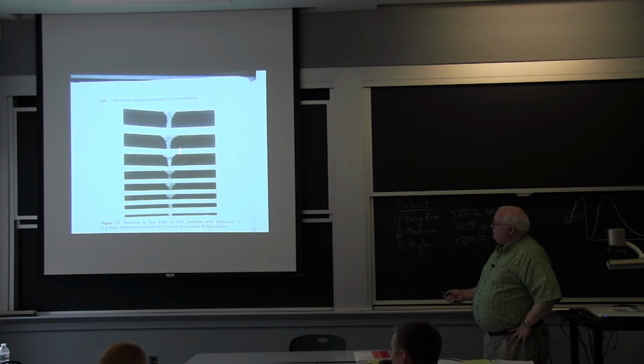So I talked about distortion, and there were a couple of things I wanted to show you. This is actually 5083 aluminum, electron beam welded from a 1/4 inch, 6.4 millimeter, to 38 millimeters, which is about 1.5 inches thick. And if you look, this is nice and straight and flat. So are these. As you get up to about, this is probably 3/8, and I told you 3/8 is where you could get the maximum distortion. You don't get distortion here because it's not a V-shaped weld. Once we start getting into the more V-shaped welds, and these are actually probably multi-pass welds up here, you get more and more distortion, okay?